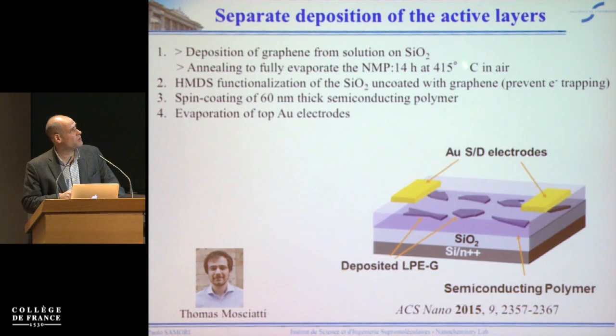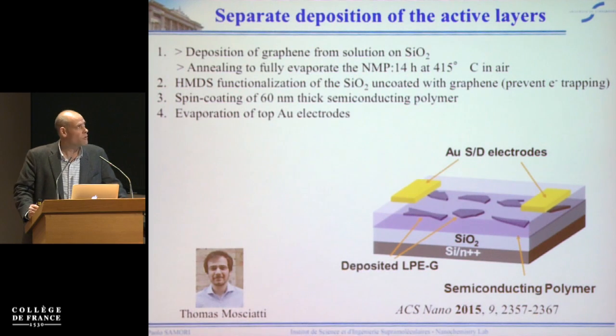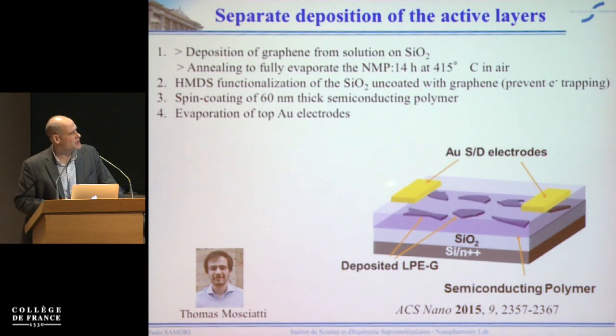At this point, we can expose the sample to 400 degrees. This is not a big issue because both silicon dioxide and graphene have no problem being exposed to such temperature. Then we do HMDS functionalization, so we functionalize the silicon dioxide with some standard alkyl chain in order to render it more hydrophobic, and then we can deposit by spin coating a given semiconducting polymer. And then we can put the top electrodes in order to fabricate the transistor.